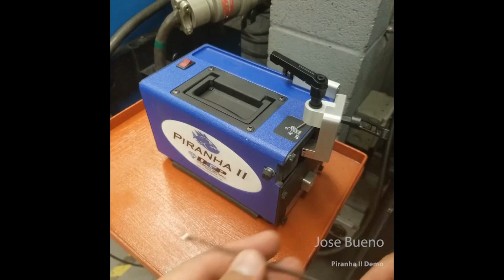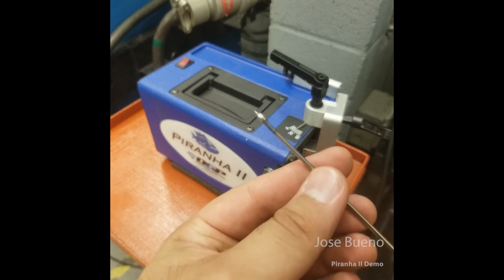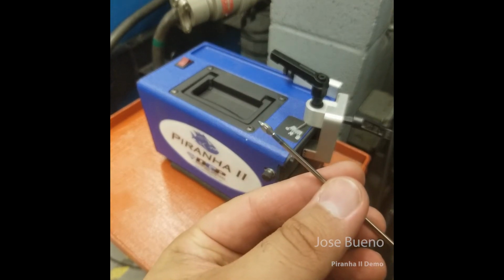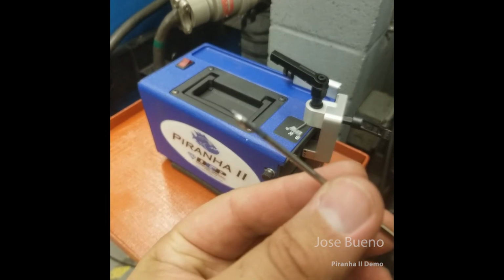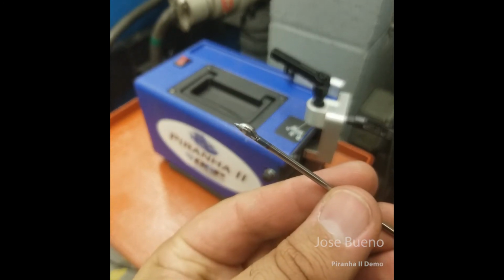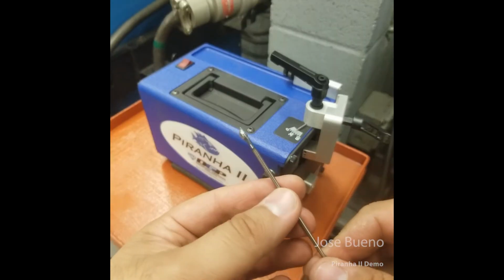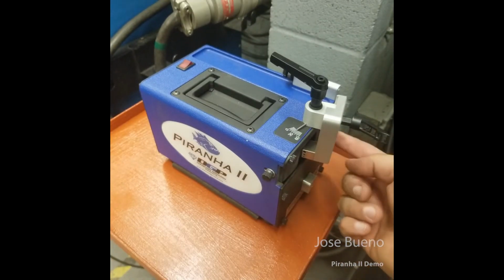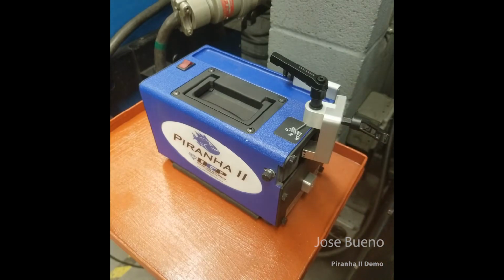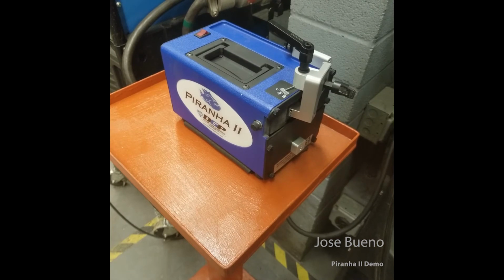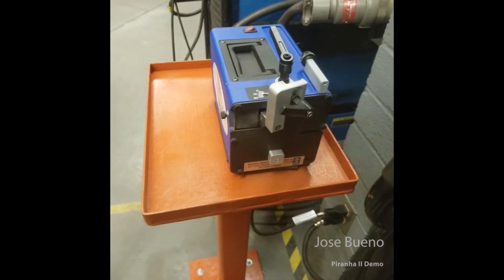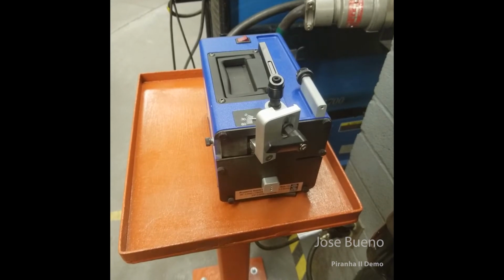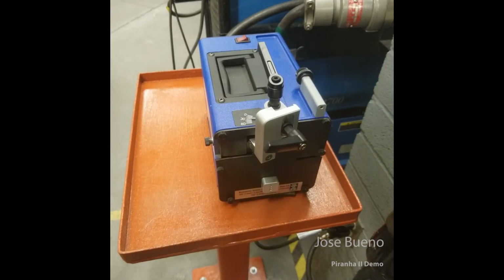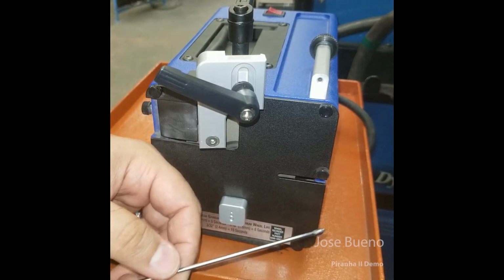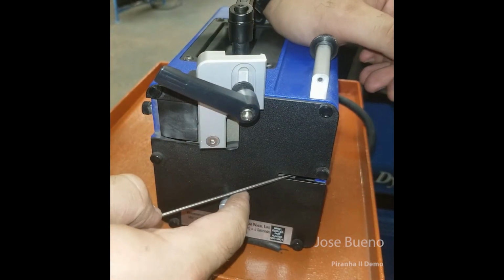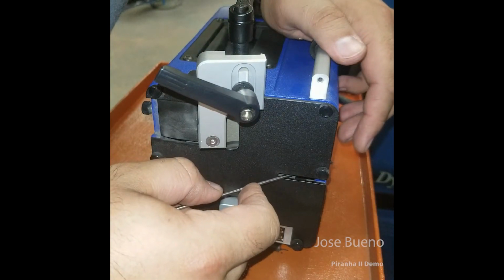So I have here this tungsten electrode that, I don't know what this person did, but they just felt like using the electrode as filler material, I guess. I'm going to show you the notching feature that the Piranha 2 has. So if we travel along to the side of the machine, you'll see a little slot in the side of the Piranha 2. And so what we'll actually do is we'll turn the Piranha 2 on. We'll let that grinding wheel spool up, and then we're going to insert the tungsten into that slot from the side, and that grinding disc is going to notch out some material in our tungsten electrode, which is going to allow us to break the contaminated part off without introducing stress fractures.